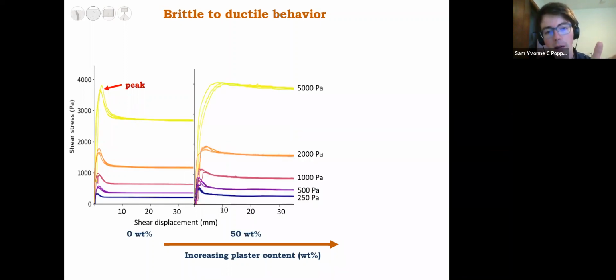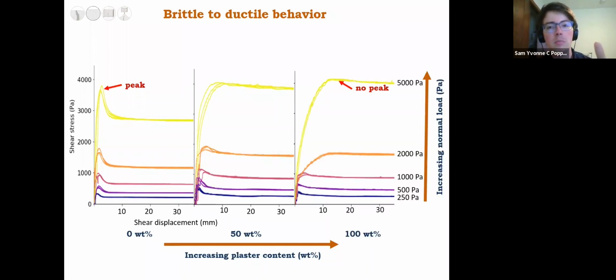But as we ran a series of mixtures going from 0 over 5 to 10, 20, 35, 50, 70, and 100 weight percent of plaster, we started noticing that as the normal load increased and the plaster content increased, that initial peak disappeared. And this is more typical for ductile behavior of materials. So basically what we saw in our sand plaster materials is as you increase that normal load and plaster content, we move from a brittle into a ductile regime, which is actually pretty similar to how we understand the Earth's crust behaves as well as we go deeper and deeper into the crust, and so analog in our sandbox.